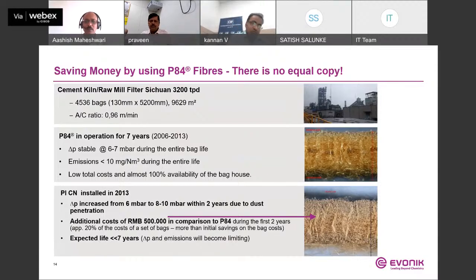This is one example from China, at a plant in Sichuan for 3,200 tons per day, where they have approximately 4,500 bags. P84 was in operation for more than 7 years, from 2006 to 2013. DP was stable at 6 to 7 millibar, emissions well below 10, and total cost was very low. There was energy saving and 100% availability of the baghouse. But they switched to Chinese PI, which is round fiber. That is one of the crucial points I would like to mention.